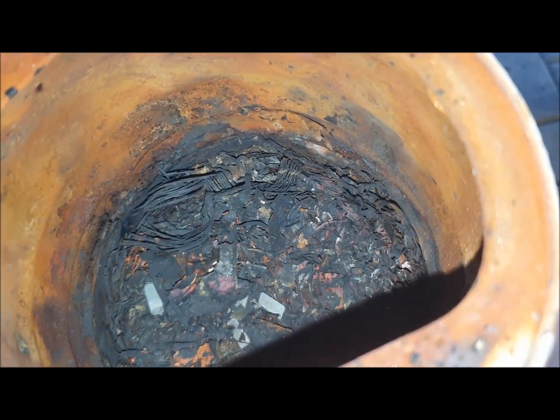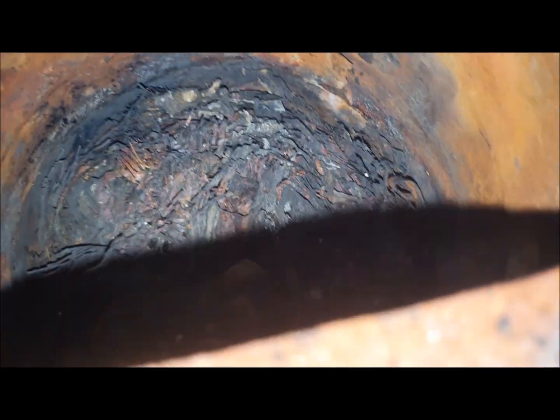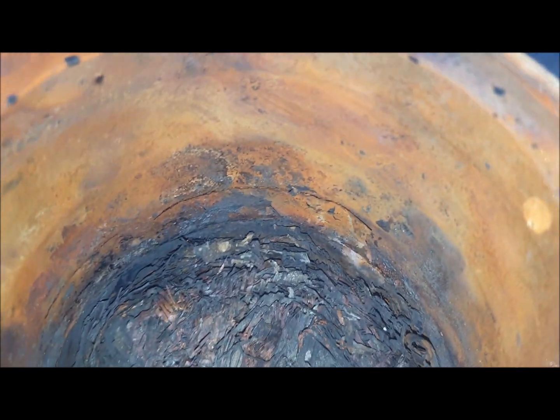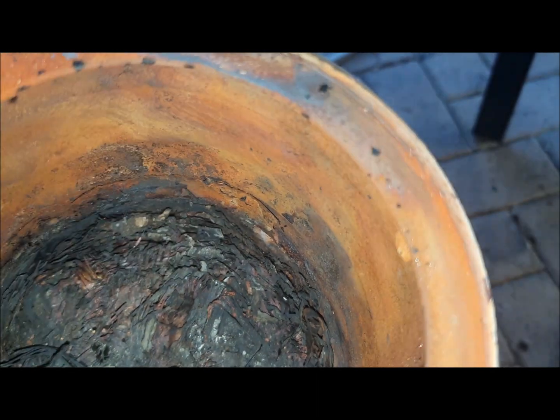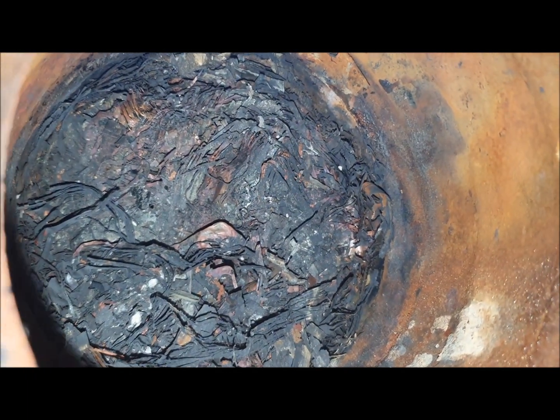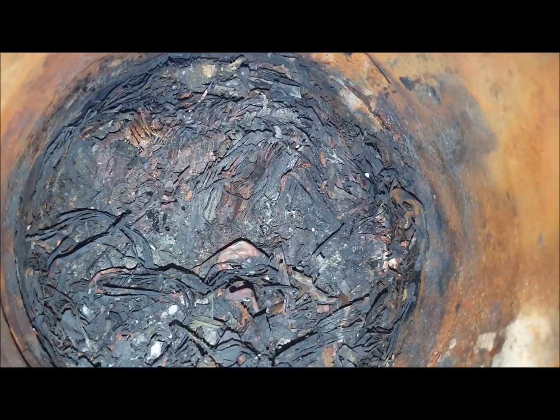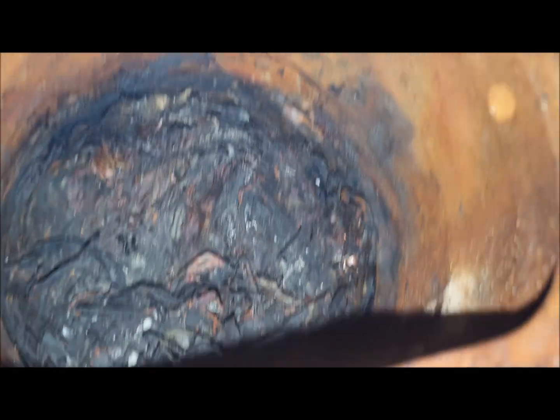They're totally burnt, and I crushed them down with an iron bar just to make sure they're brittle. You can see copper in there. Can't see any gold yet. You can also see on the edge of the tin, the tin is flaking into the ashes — that's the problem with using these tins. I wish I had something made of stainless steel, but since there's tin in there and tin is a nightmare when it comes to refining gold, I'm going to soak this in hydrochloric acid.